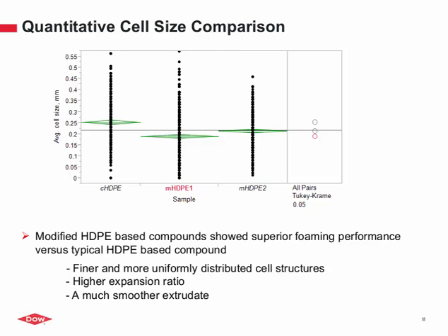So what we see is that these modified compounds showed superior foaming performance versus the typical HDPE system, with finer and more uniformly distributed cell structures and a higher expansion ratio. I think that will come in the next slide. And from the images, we also saw a very smooth extrudate coming out of the line.